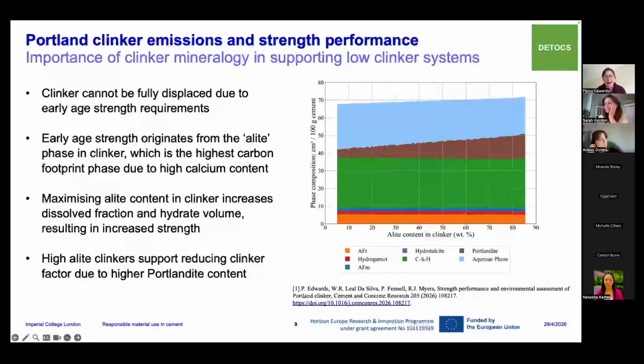And that brings us back to clinker, which gets a bad rap in the cement story because it's bringing all of the emissions, but it's super reactive, and we know the chemistry really well, so we know how it works. It's got a wide definition of what can be a clinker, and it's made of these reactive calcium silicate phases. And the most reactive phase is known as alite, which is tricalcium silicate, which is highly reactive, but it also has the highest carbon footprint of all of the clinker phases due to its calcium content, which again creates a trade-off between emissions and performance.